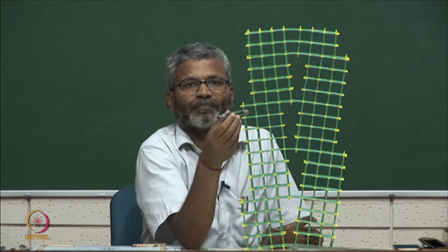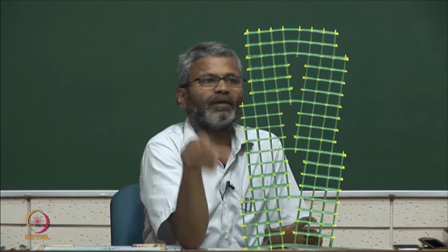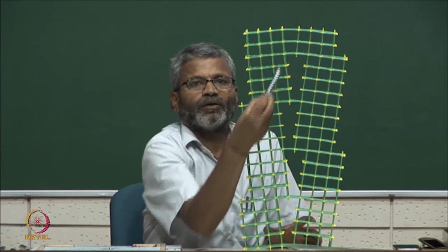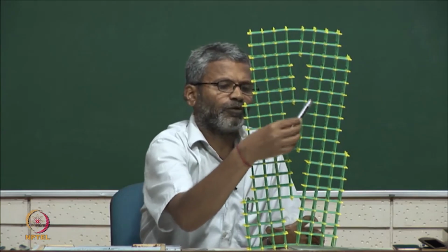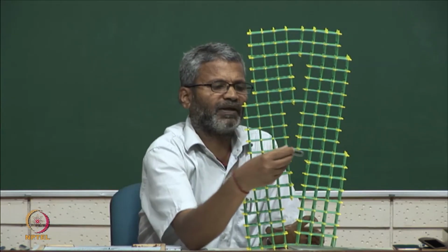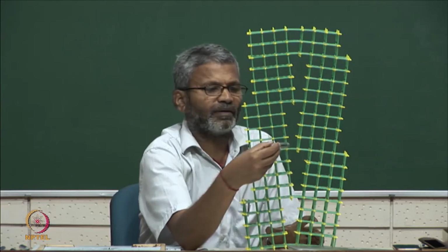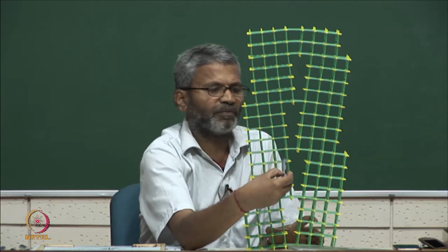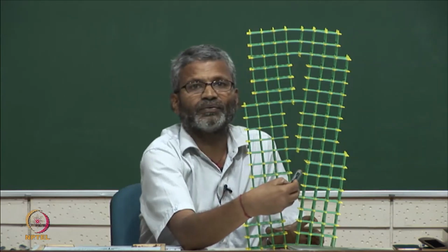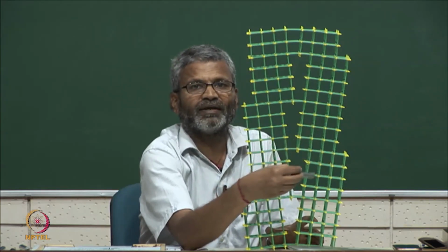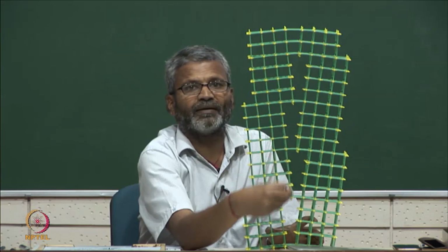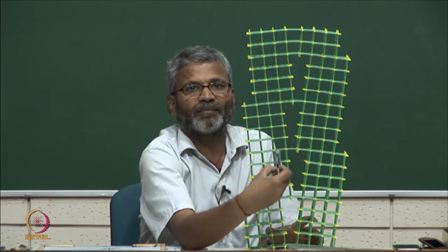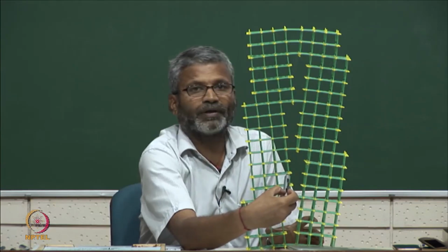The tilt angle is not very small here, but still you can see the configurations as you get close to the boundary. If you look at this plane, this plane comes and abruptly ends here, but the neighboring planes continue. So, locally here you have an arrangement like an edge dislocation, because this plane abruptly ended, and the neighboring planes are continuing and going down.